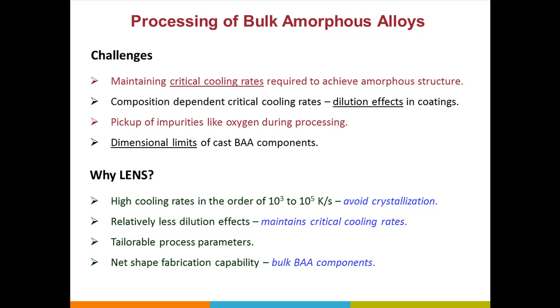Now this is inherent in LENS. Because we go to very high temperature, we can cool things really fast. And because we are doing microcasting, we don't actually change the composition. So we felt we should be able to make bulk amorphous alloy parts using LENS pretty easily. We could accomplish in LENS between 10 to the 3 to 10 to the 5 Kelvin per second cooling rate, which is quite challenging for most any system you can think of.